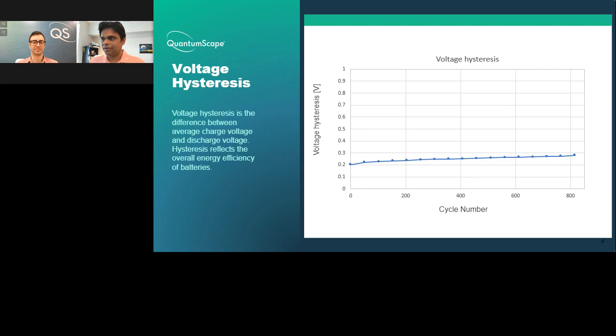I think the safety aspect certainly depends on a few factors. One is the cell certainly still has some liquid electrolyte on the cathode side, of course, albeit now you've removed the electrolyte on the anode side. So certainly the safety profile for a cell that has overall lower liquid electrolyte content is better. And of course, now you have a solid electrolyte that stops lithium plating and dendrite formation as a failure mechanism. So I think that also provides another layer of safety in terms of suppressing one of the failure modes that is present most commonly in lithium metal cells, but also in lithium ion cells, where lithium plating and then eventually growing through the separator and shorting the cell is one of the failure modes.